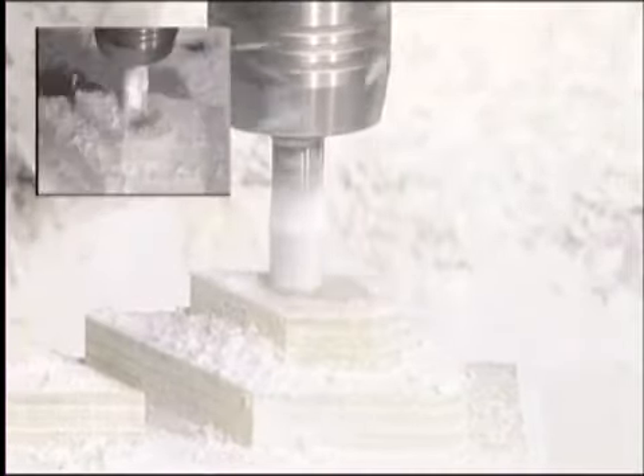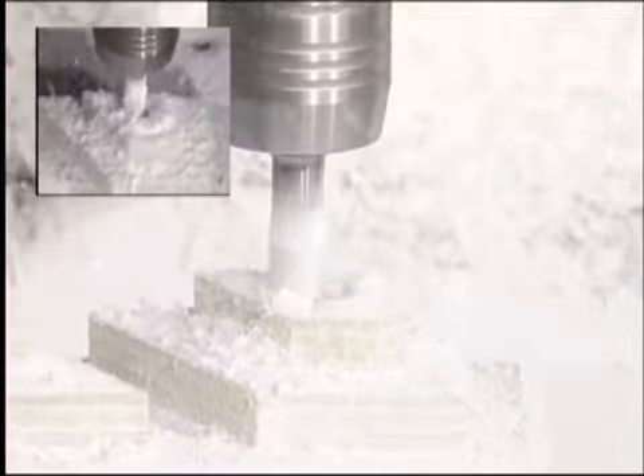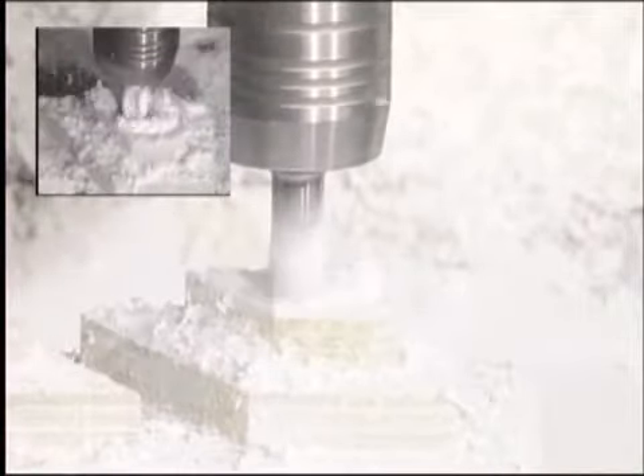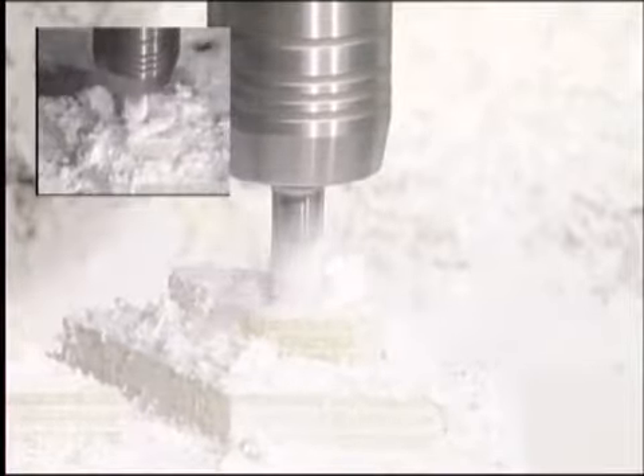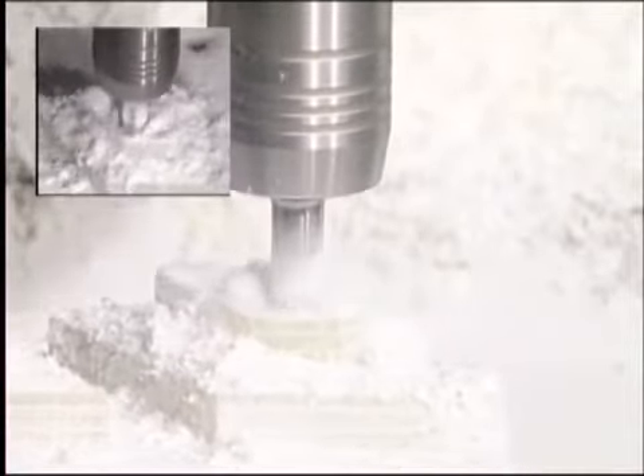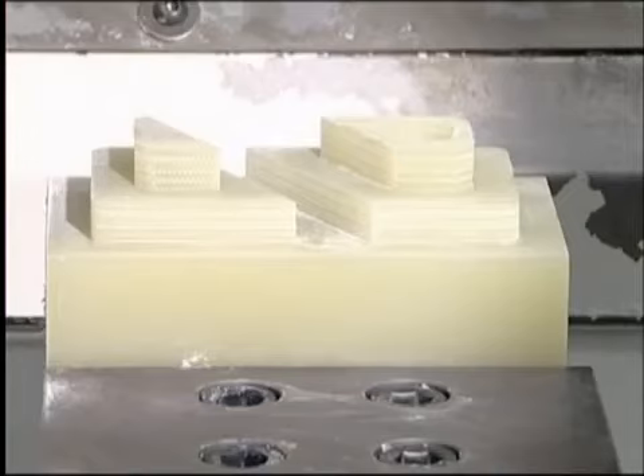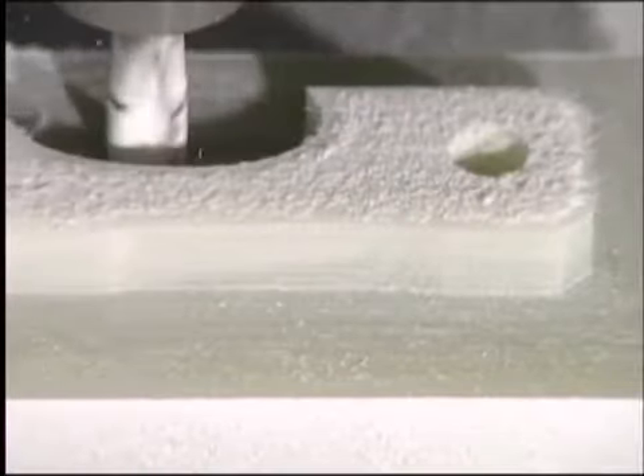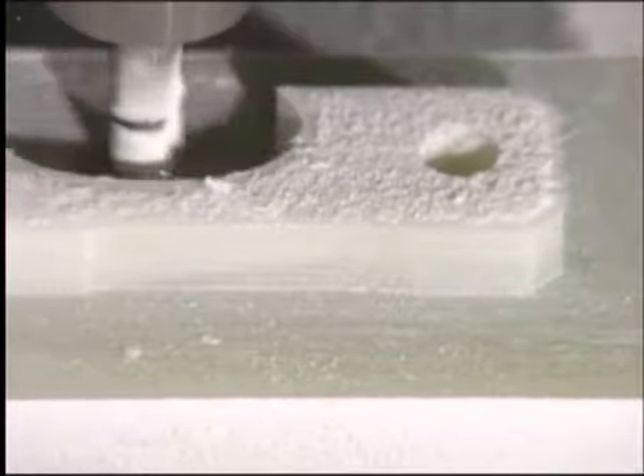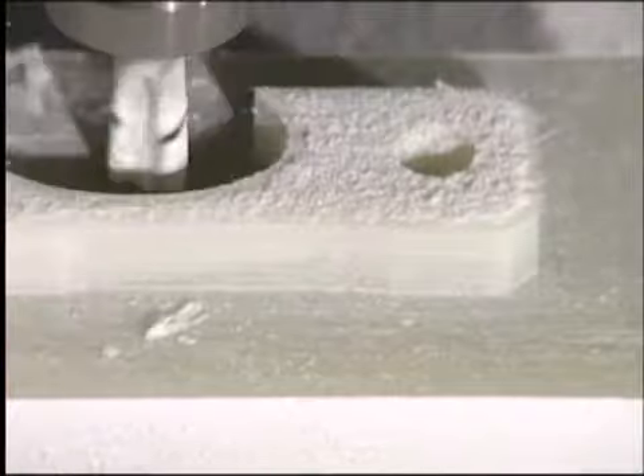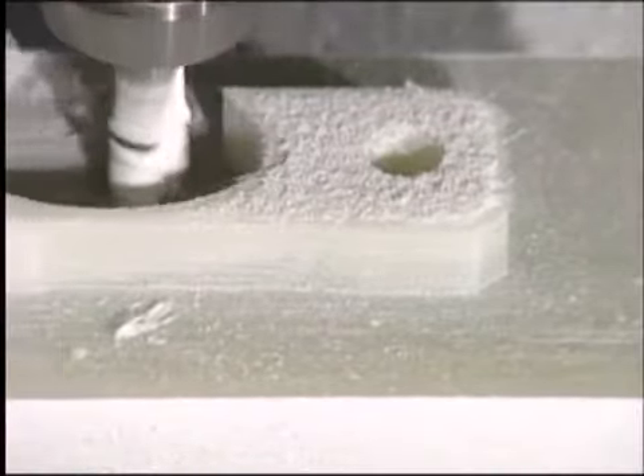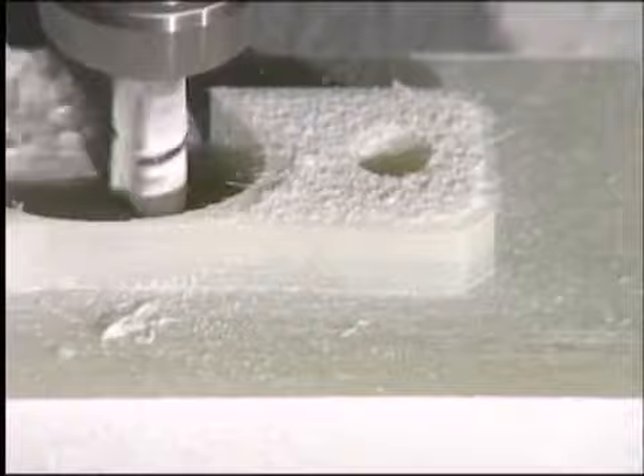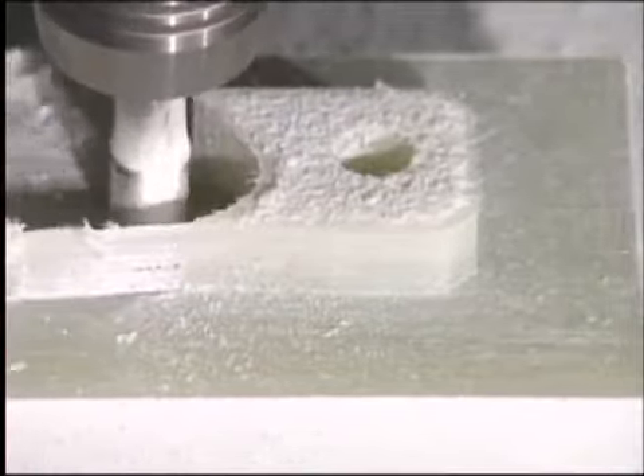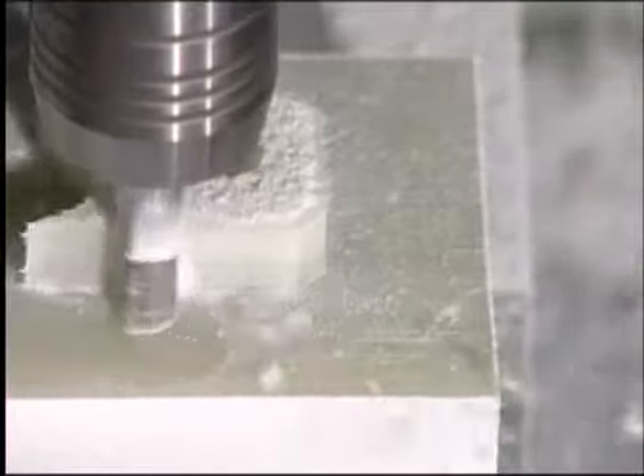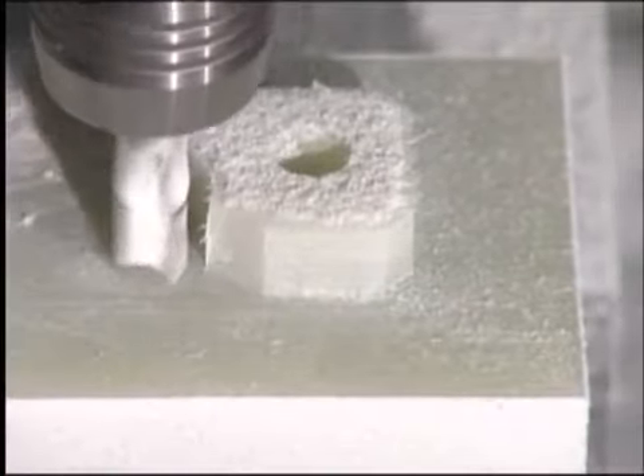Compared to carbide, our Becker TFC diamond edges improve tool life up to 50 to 100 times when machining this abrasive material. Tool offsets and changes are dramatically reduced. The edge and surface finish attained hereby eliminate the need for any secondary operations. There's no evidence of wear at the cutting edge, although dry milling is not recommended when using TFC diamond.